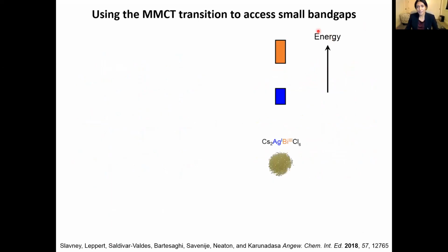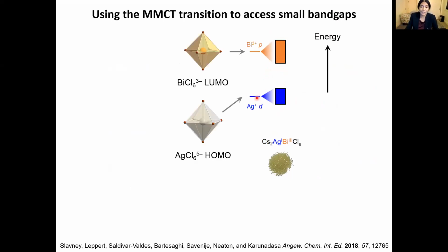So this is my very simplified band structure of the silver bismuth chloride double perovskite, where I'm simply trying to show you that the band gap transition is an electron moving from silver to bismuth. So I can extrapolate from this band structure to the molecular orbitals that form the bands. And I can say, well, this is the approximate energy of the silver hexachloride highest occupied molecular orbital. And this is the approximate energy of the bismuth hexachloride lowest unoccupied molecular orbital. And there are all kinds of spectroscopies available that allow us to actually figure out what these energy levels are.